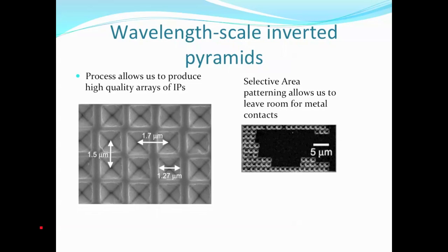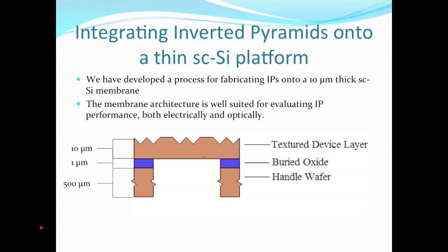That way we can leave room for metal contacts, because you don't want to lay metal contacts down on an inverted pyramid texture. So now that we have these inverted pyramids, we need a thin crystalline silicon platform to test them on. We've developed a 10 micron thick, single crystalline silicon membrane that's supported by a thick handle wafer. Now this membrane is very well suited for testing light trapping, both optically and electrically.